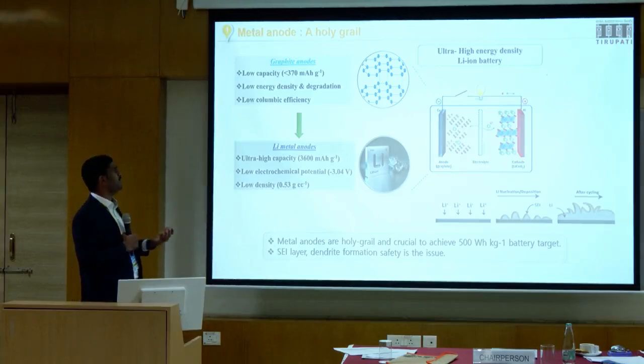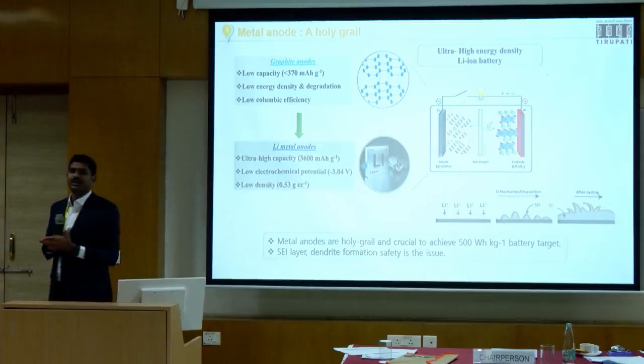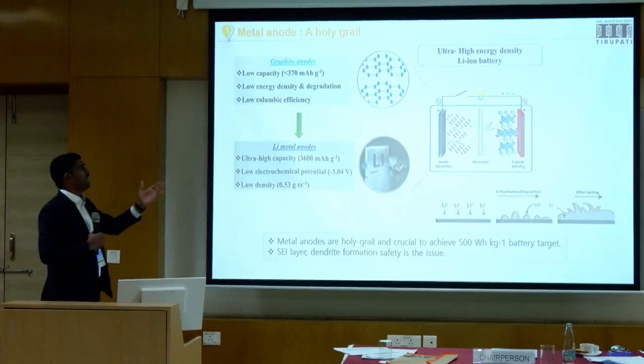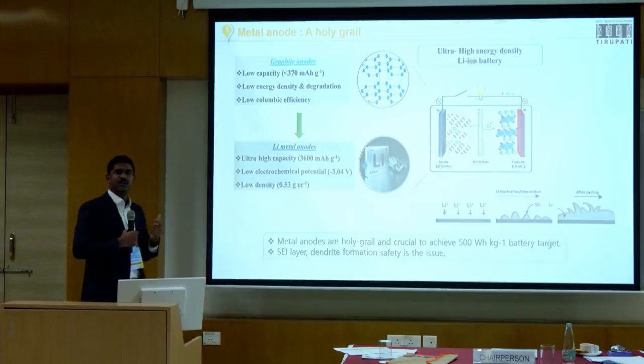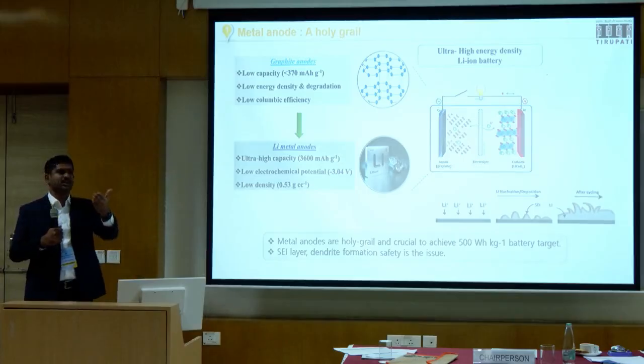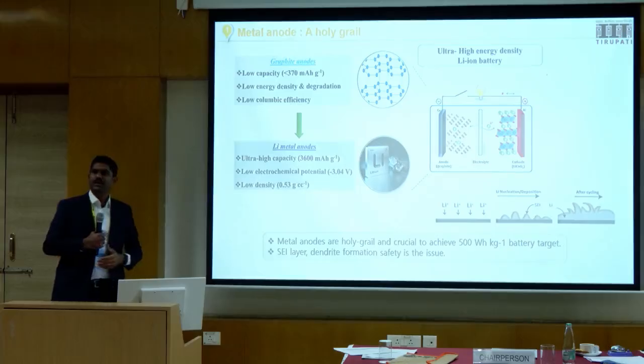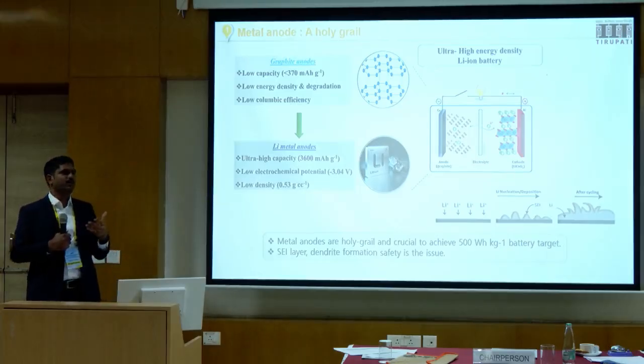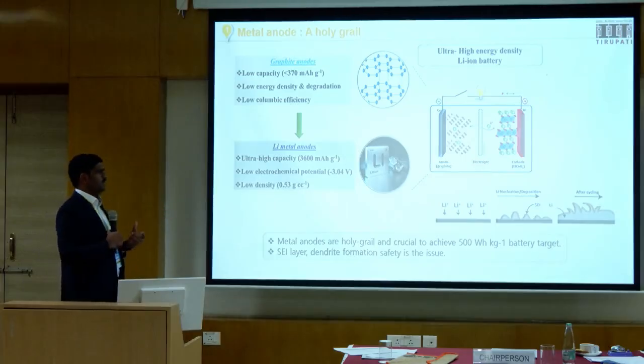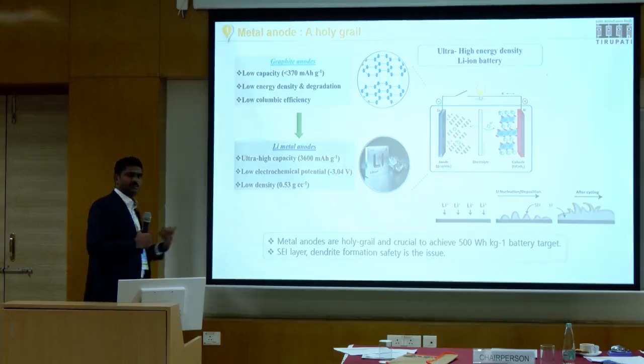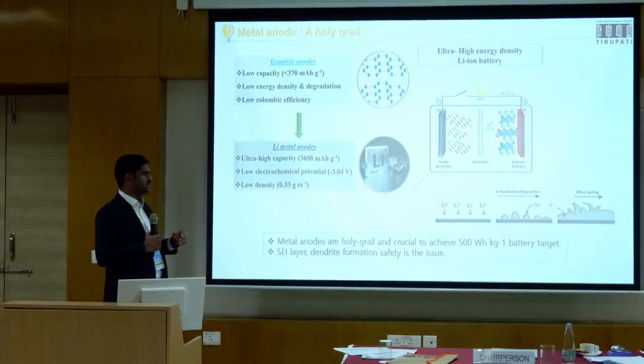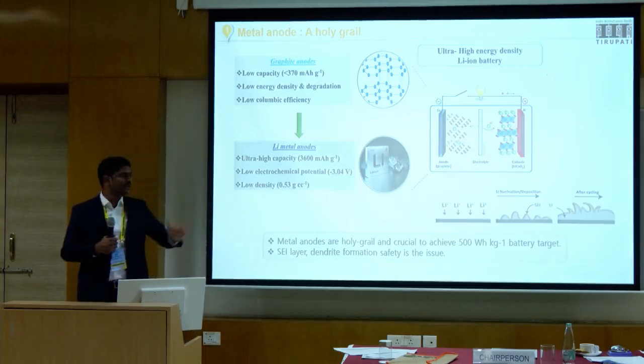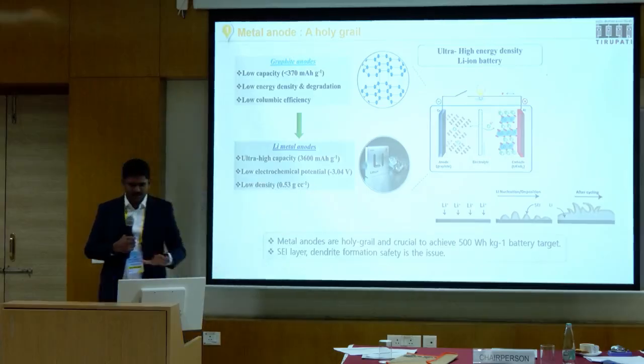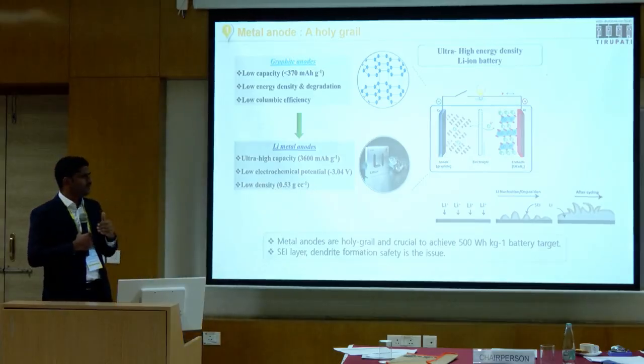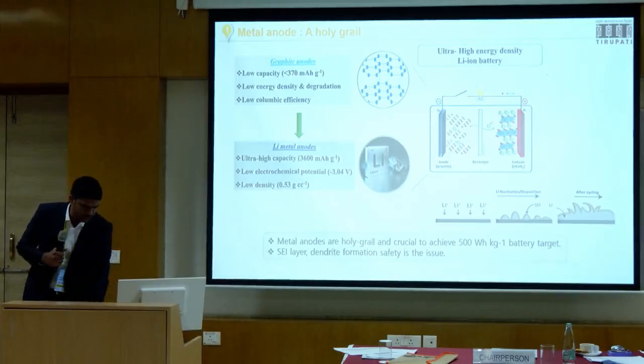And why this is happening is that when you move from graphite to lithium anode, you can obviously see the theoretical capacity of lithium metal is 10 times higher than graphite. Per gram of material, you can store at least 10 times higher energy than graphite. Obviously, lithium being the lightest element in the periodic table, you will be able to realize the smallest or lightest battery that can power any electric vehicles or energy storage devices. But as I said, the problem here is the reactivity. You can see here that conventional lithium metal can form dendrites much more severely than modern rechargeable batteries.